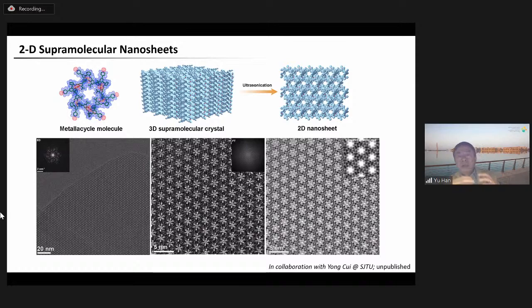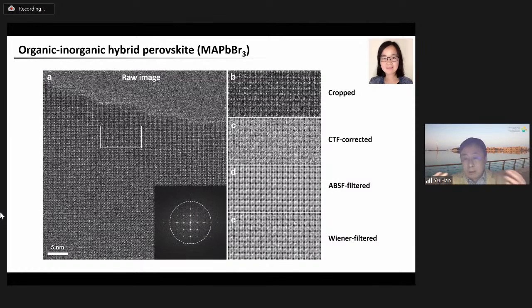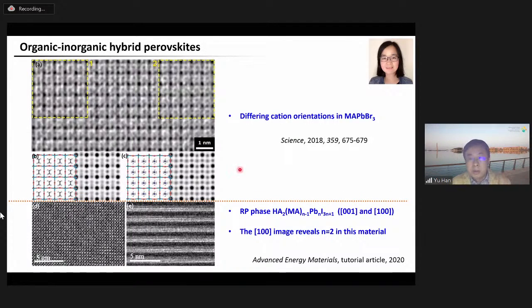Organic-inorganic hybrid perovskite materials are very important because of their optical and electronic properties, right? But they are similarly sensitive to electron beam as MOFs, so it's not easy to get atomic resolution for this kind of perovskite material. While using our method, we were also able to image them at atomic resolution. From the images, we can observe different cation orientations in a hybrid perovskite material, and we can also identify the n values of the RP-phase perovskite material. So perovskite is also manageable.